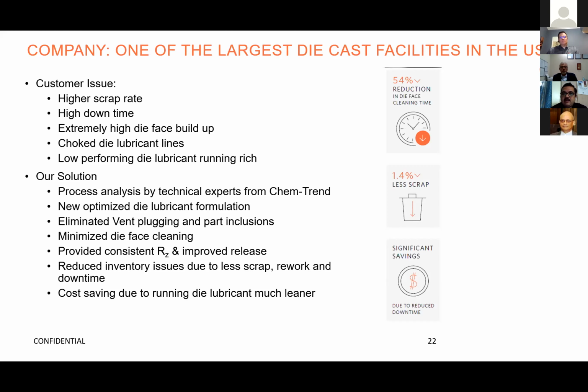The customer was very happy because they saw a 54% reduction in the cleaning time, the amount of time they took to clean the die surface, since they had to keep the die clean for a very good locking force. They also reduced their scrap rate by around 1.4%. The customer was very happy because we provided a very consistent surface finish, improved part release, and reduced their inventory issues because we reduced scrap, rework, and downtime. So this is how, when we make a die lubricant, we apply it in the field and help the customer save more money. This is what we intend to do for our customers.